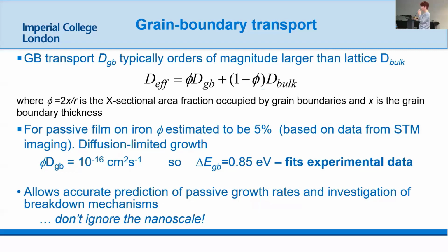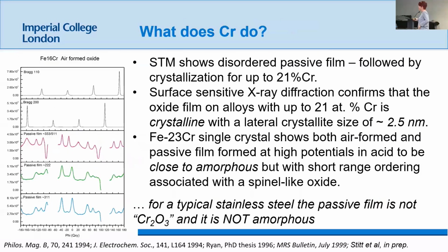So this approach gives us an accurate prediction of growth rates, potentially is useful for investigation of the breakdown mechanisms. But it really tells us, well, one, use the right technique if you want to measure something. And two, please don't ignore the nanoscale in corrosion systems. So I'll just briefly talk about what chromium then does and why chromium, the iron chromium system in particular, gave rise to so much controversy.